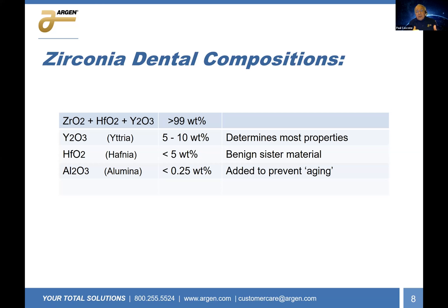Now, the actual dental zirconias are very, very simple. They involve zirconia, this other material called hafnia, and then yttria. Hafnia is a benign sister material with zirconia. Sometimes nature doesn't allow us to make things 100% pure, and that's the case here. So no matter what we do, we're always going to have some hafnia in the material. It doesn't affect the strength. It doesn't affect the translucency. It just is a sister material with zirconia, and it's there. Because it's there in greater than 1%, we report it. Generally, most people will reduce it to less than 2%, and that's a sufficient feedstock.